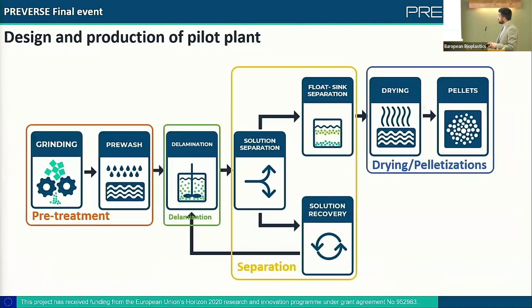The second task concerns the design and the construction of the pilot plant, where the delamination of the developed material takes place, and the process is divided in 4 blocks: the pretreatment, the delamination, the separation, and drying and pelletization. The pretreatment is necessary to make the material processable and transportable, including the grinding and the pre-washing of the material. The first process is grinding, and this makes the material easy to handle and increases the contact surface with the washing solution.